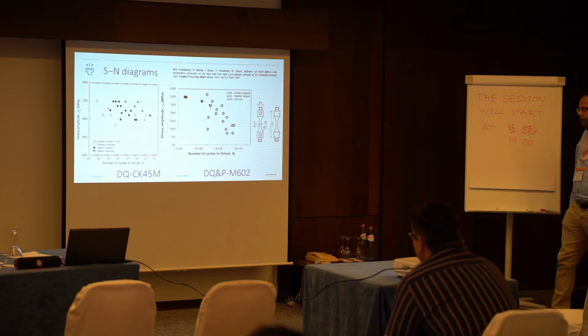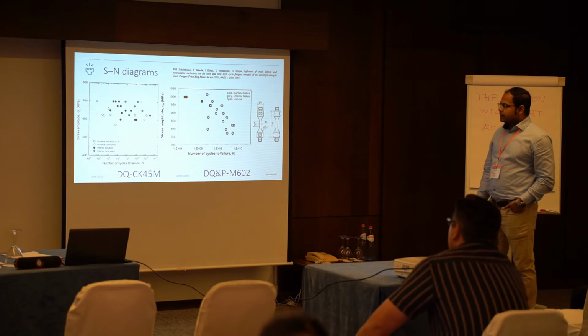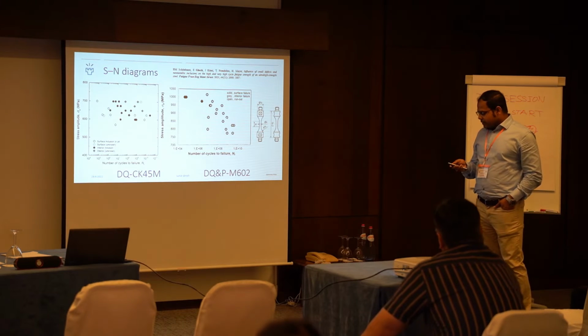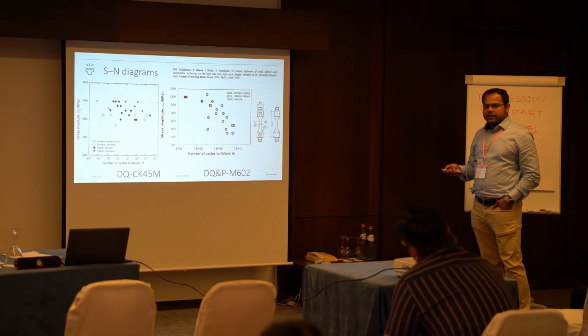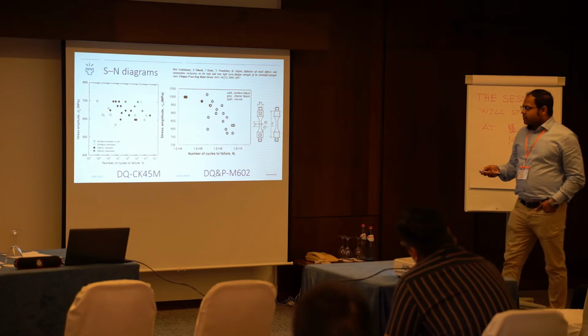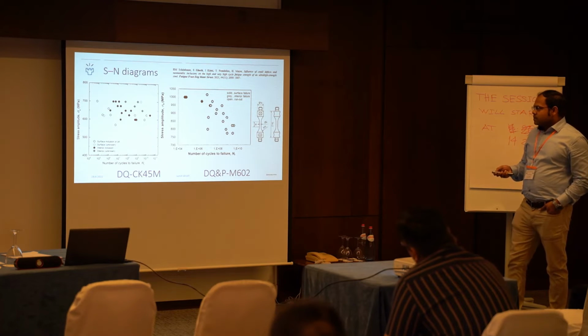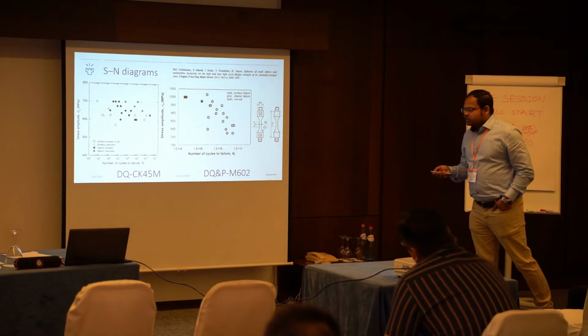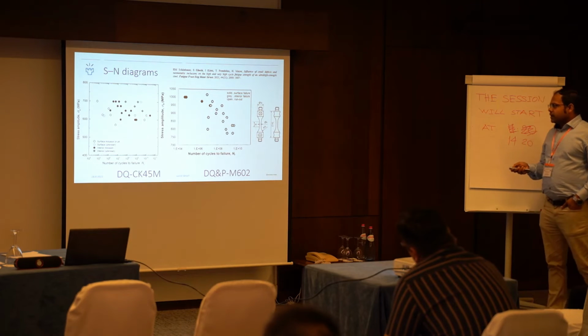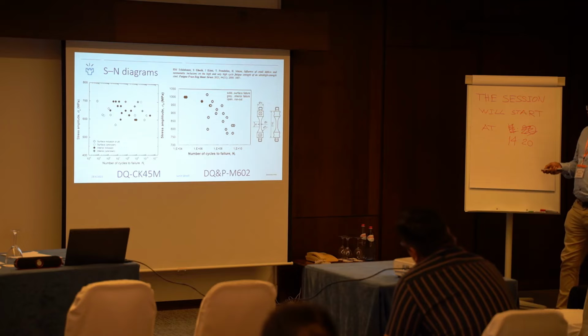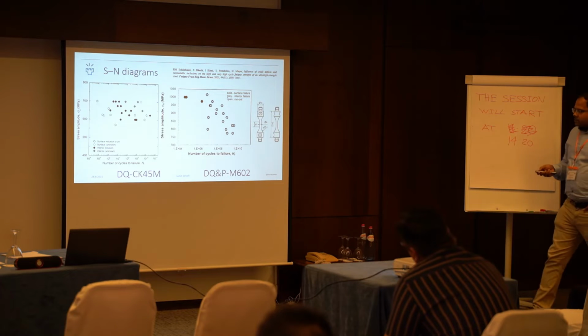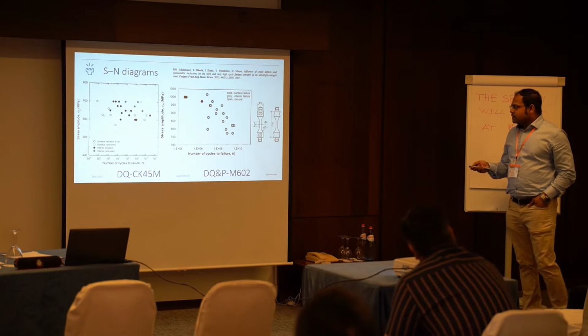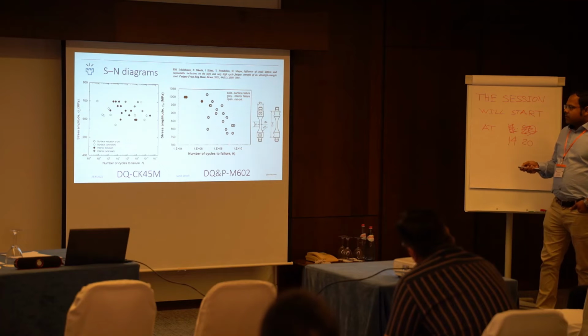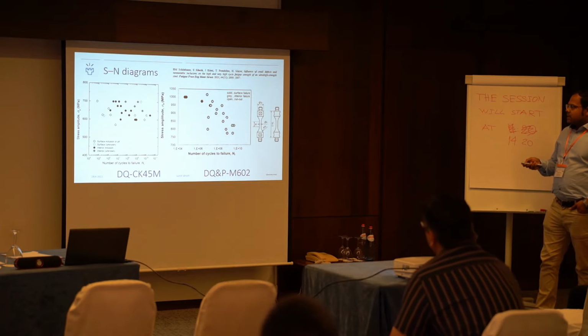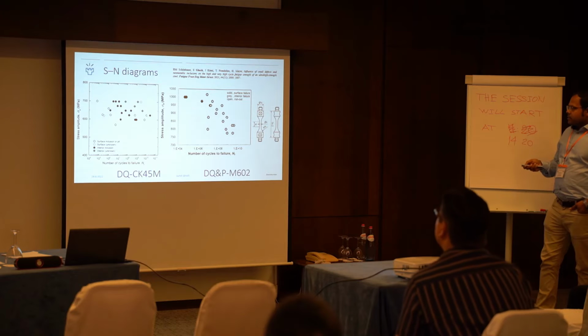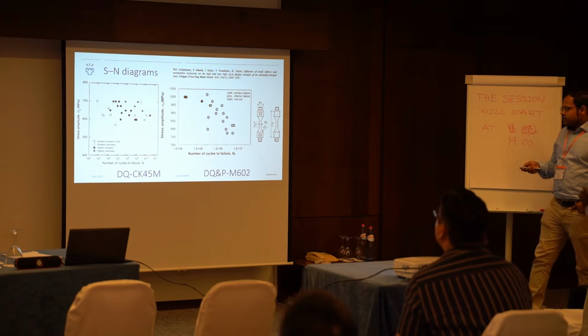And so finally, when we conducted the very high cycle fatigue in both conditions, here you can see, despite having a very high yield strength, these materials survive 10^10 cycles with a stress amplitude of only below 650. Whereas in the case of DQ&P steel, although the yield is slightly lower compared to this CK45M steel, this material survives the same number of cycles with a stress amplitude much higher than CK45M steel. In this case, it is in the range of 750.